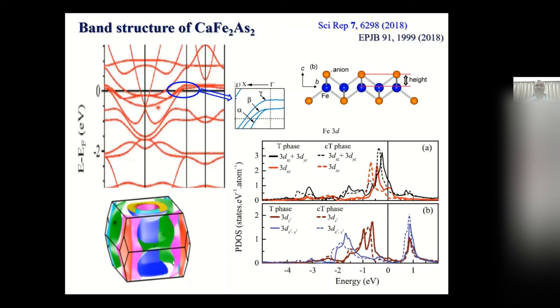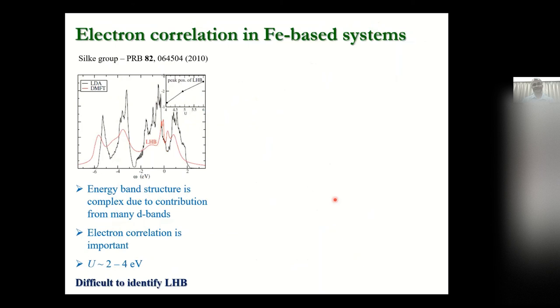The reason is that the relaxation time we are measuring is of the order of 100 femtoseconds to picoseconds — at this timescale, electron-electron interactions have already died down. We are looking at electron-phonon interactions. Itinerant electrons are more exposed to the lattice, so they have much more scope to dissipate energy compared to localized electrons — that's the reason we get this different behavior. This is one experimental demonstration of orbital-selective behavior: a lot of people have been talking about orbital-selective Mottness, meaning if you have different orbitals with different hybridizations, the effective mass and correlation-induced effects will be different for different orbitals.